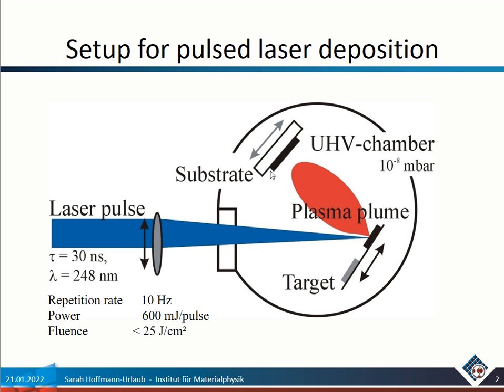The repetition rate of the laser is up to 10 Hz, and the maximum power per shot, or per pulse, is up to 600 millijoule when the laser is freshly filled, so you can reach fluences or energy densities up to 25 joule per square centimeter.